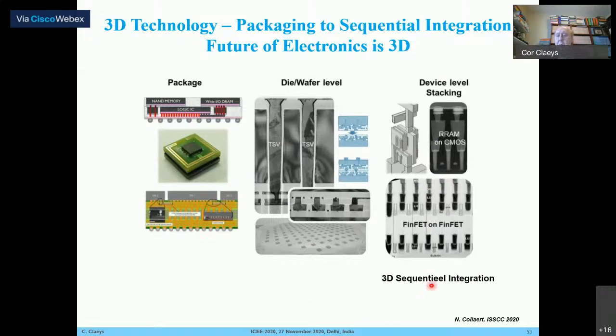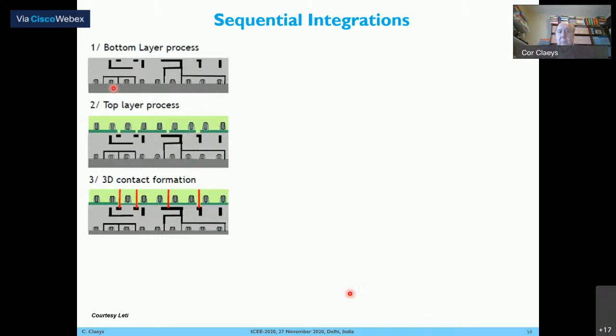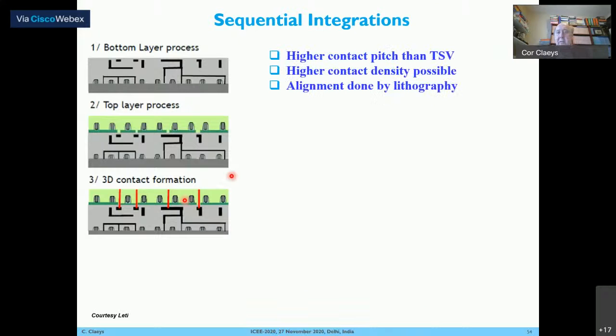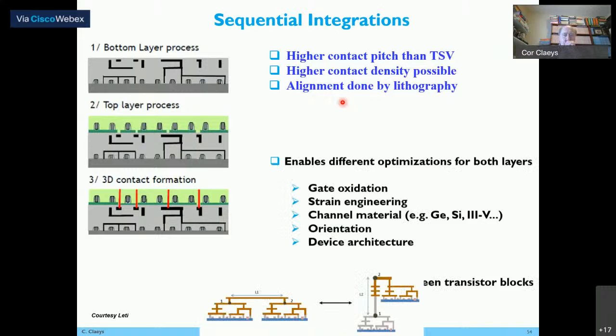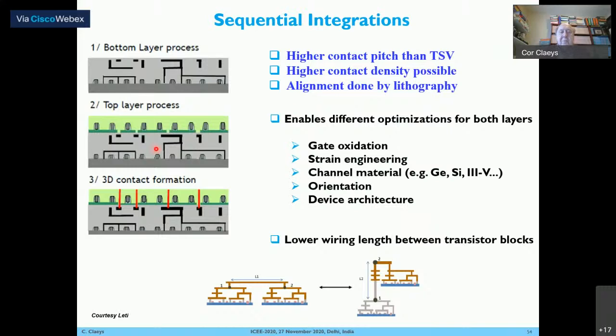That means you are going over to three-dimensional integration. How is that working? Well, you have a bottom layer, let's say a silicon wafer, where you do the normal standard processing. Then you grow a layer on top of that. You do processing in the top layer, and then you do the final metallization. In that way, you get a higher contact pitch, higher contact density, and the alignment is done by lithography, not by bonding. That gives you the possibility to have different types of devices in the top layer and in the bottom layer. You can play with the gate oxide, strain engineering, different types of channels, and you're gaining in the wiring length between the different transistors.